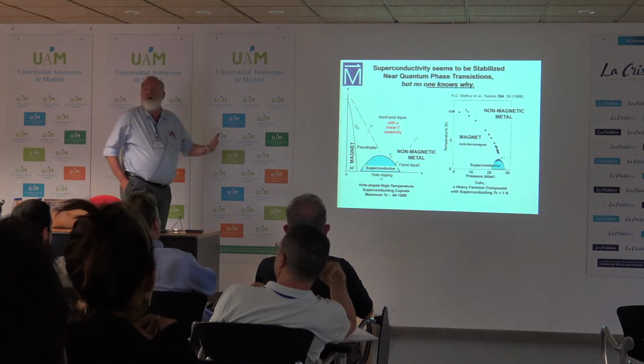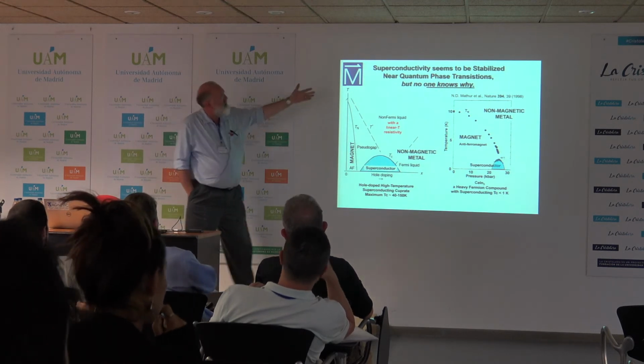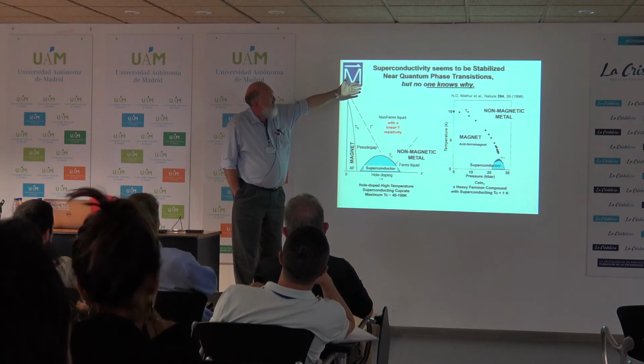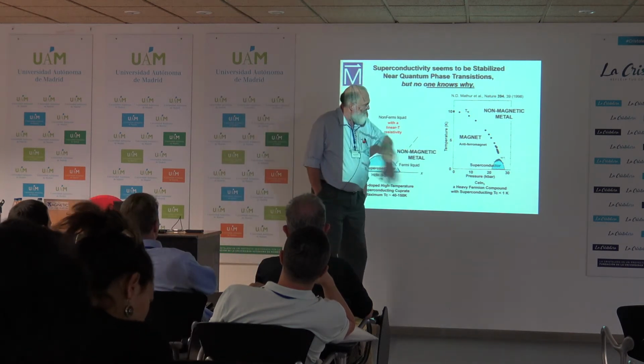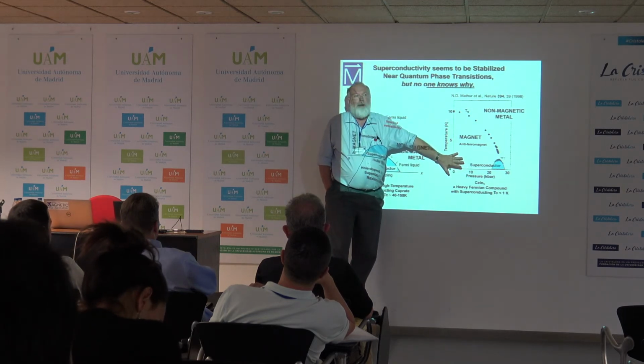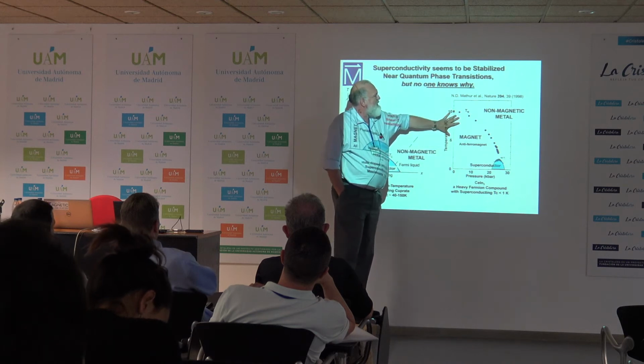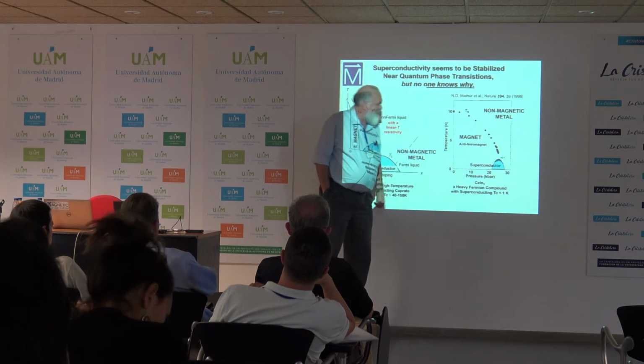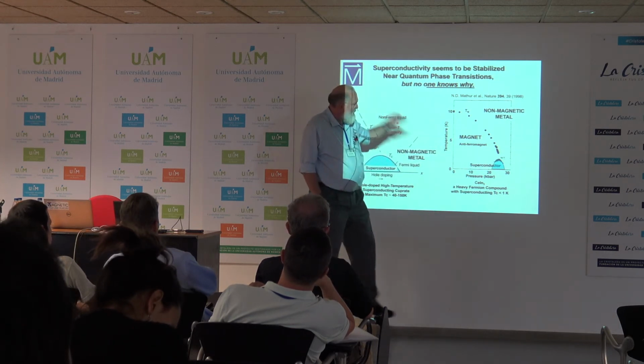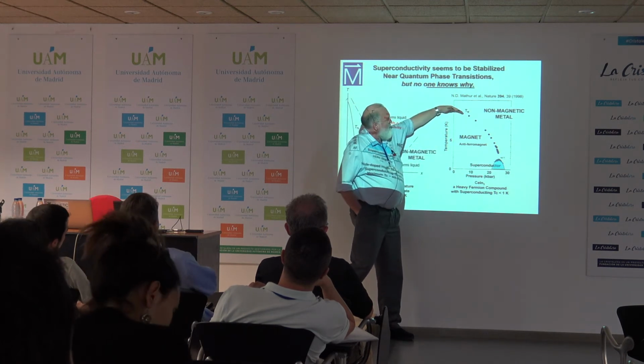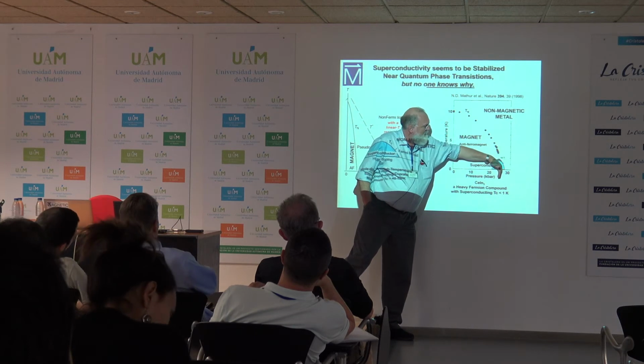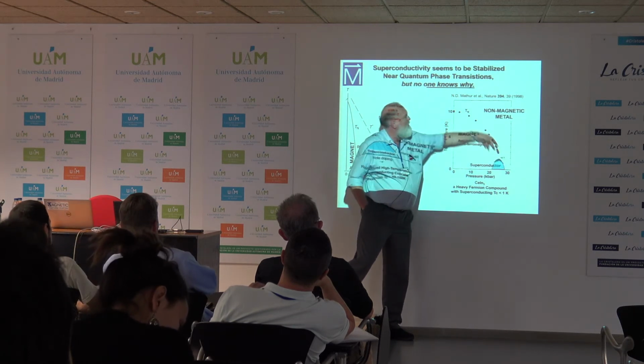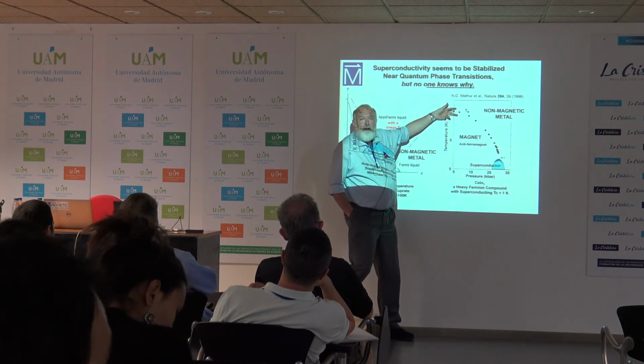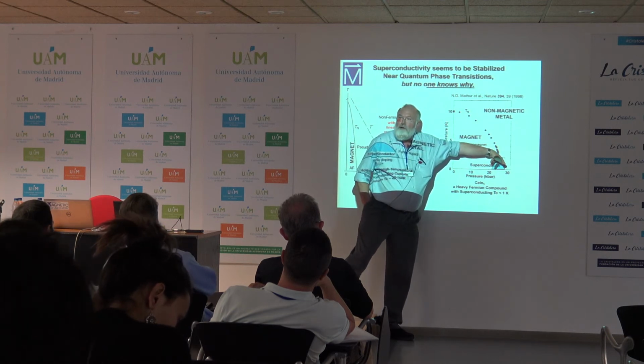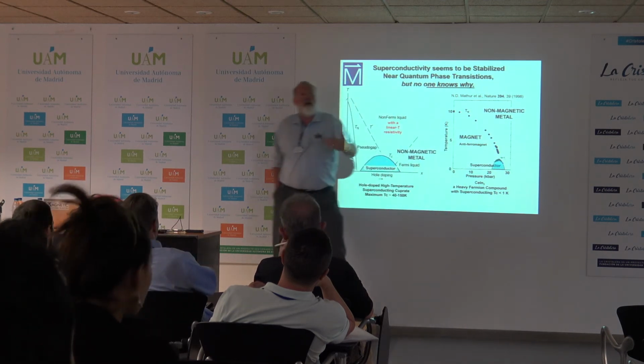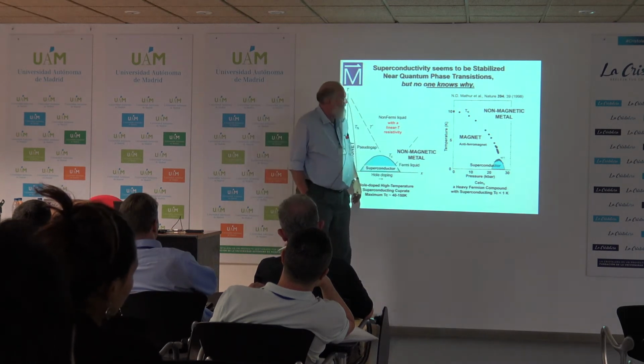And as Tony mentioned, there are quite a few other physical systems that show this phenomenology of superconductivity seemingly stabilized near quantum phase transition, and no one really knows why. This is an example that was not in the zoo of compounds that Tony showed. These are the heavy fermions. So these are three-dimensional systems that have F electrons in them that give you a heavy mass. And this is work from Gil Lonzarich's group, where his tuning parameter is pressure. And he was noticing that the transition to antiferromagnetism was dropping with pressure, and he wanted to go to that point where the phase transition drops to zero, because we have a theory of phase transitions that are driven by temperature, but we don't really have a theory of phase transitions that are driven by variation of some parameter at zero temperature. So quantum fluctuations would presumably play a role.